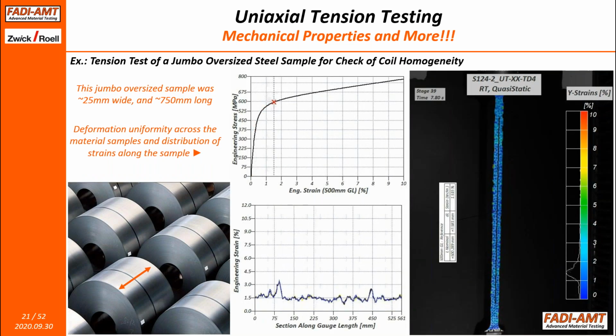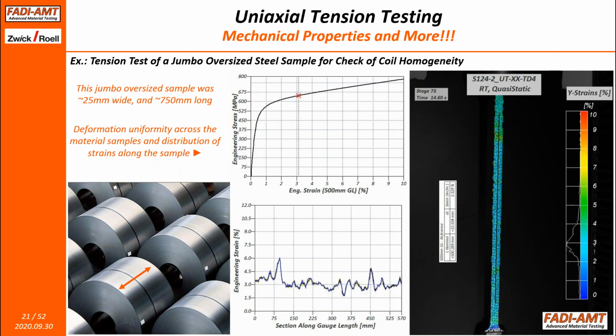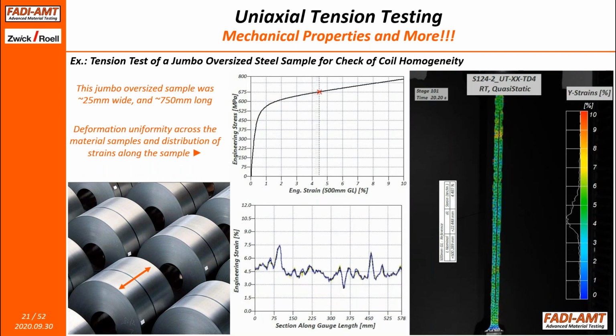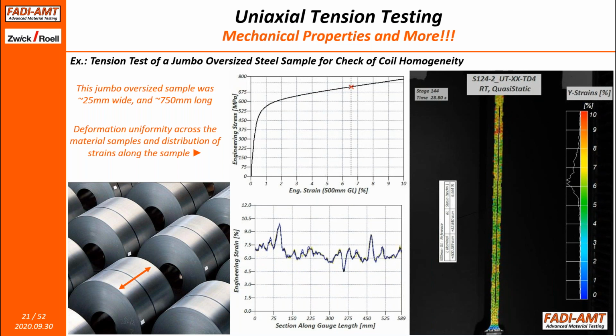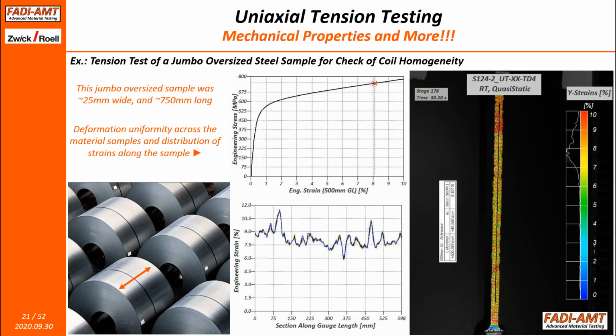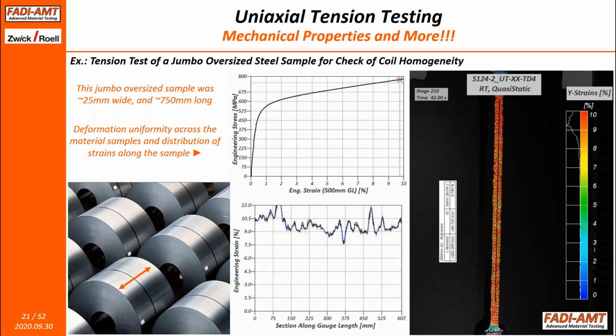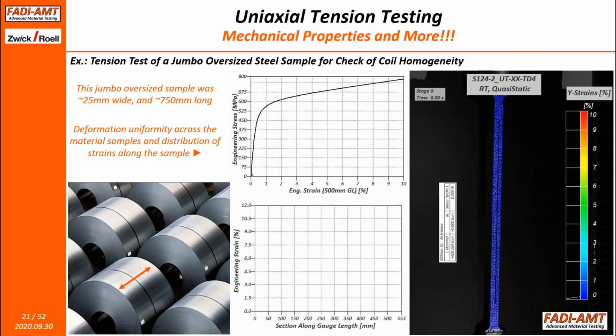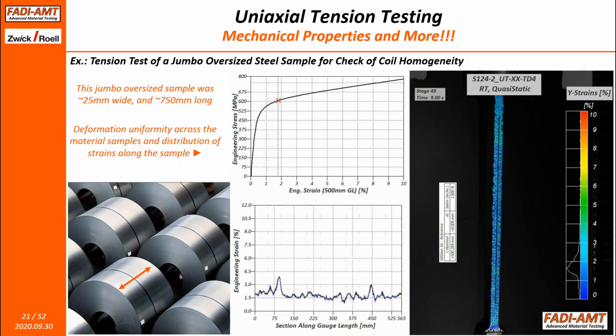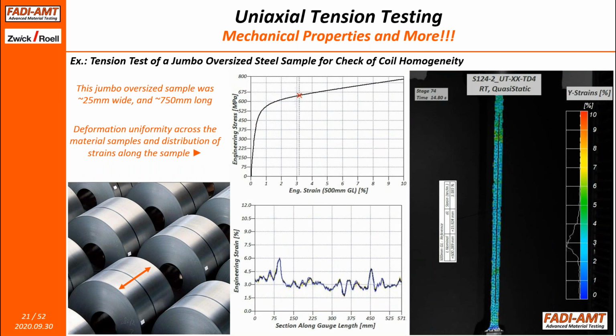Last example on the first type of tension tests I'm covering today is basically testing extremely large samples. And this is something done in characterizing an entire coil. In this particular case, this sample was about 750 millimeters long, and it was taken across an entire coil. And the idea was to try to test the sample, not necessarily to failure, but rather to test it to a particular point in order to evaluate the uniformity and homogeneity of the material.